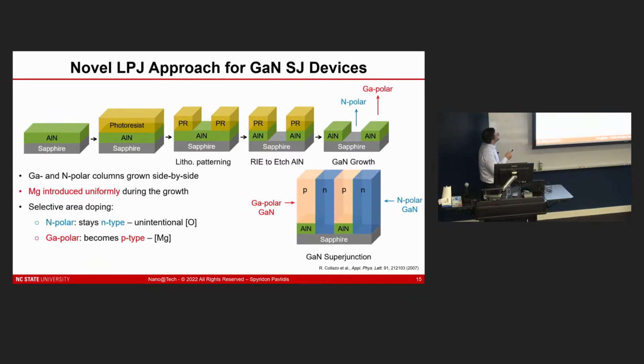We can take a nitride template, pattern it, and then go directly to a growth step where we can grow gallium polar and nitrogen polar layers or regions side by side in a single growth step. And while doing that, I can, for example, introduce magnesium as an acceptor impurity. For the gallium polar regions, there will be low background oxygen. Magnesium will be incorporated, and that region will become p-type. Whereas for the nitrogen polar regions, I'll still have oxygen incorporated, which will be net n-type. And so I can basically create N and P regions side by side with each other.